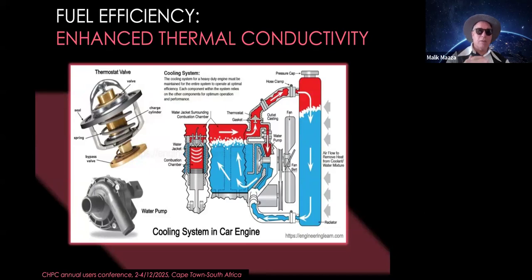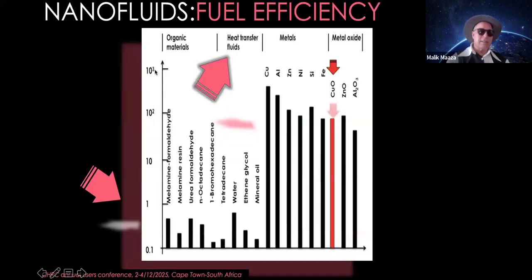Because the water, yet the water has the highest thermoconductivity among all coolants, its thermoconductivity is low, less than 1 watt per Kelvin per meter. As you can see, this is the thermoconductivity of different fluids, organic materials and heat transfer fluids, as compared to metals and their oxides. You would see that for all the normal coolant fluids, the thermoconductivity is less than 1 watt per meter per Kelvin. But that of metals and their oxides is 2 to 3 orders of magnitude higher.